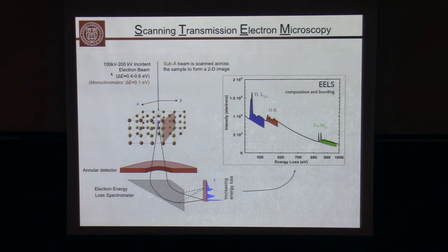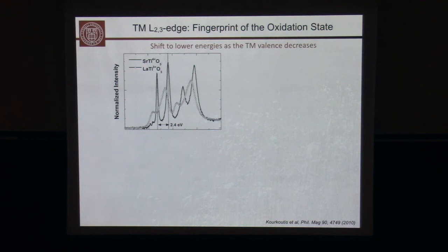So one example is that of titanate. So here is lanthanum titanate compared to strontium titanate, where the formal valence changes from 3+ to 4+. And what we are mapping is the titanium L2-3 edge. Okay? And so what you see right away is that the fine structure of that edge dramatically changes. And it turns out for these transition metal oxides where hybridization is less important and the ionic picture dominates, we can use these fingerprints to track the formal valence as you go into any point on the sample.